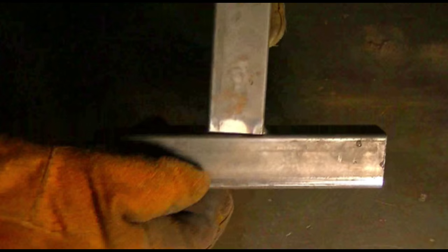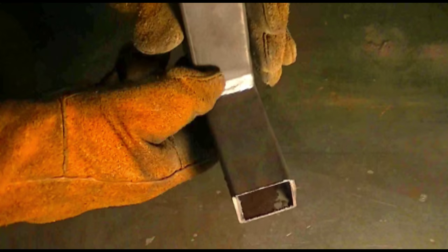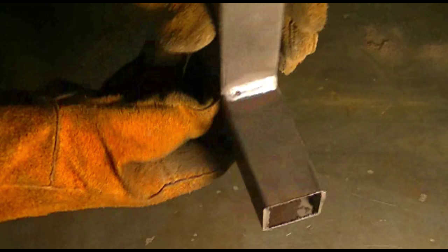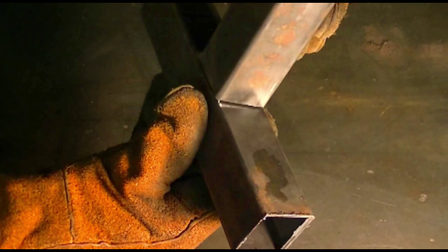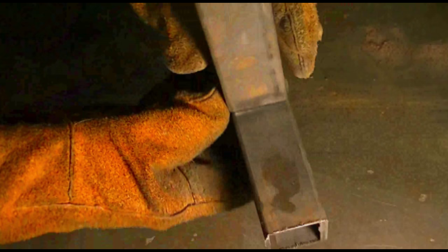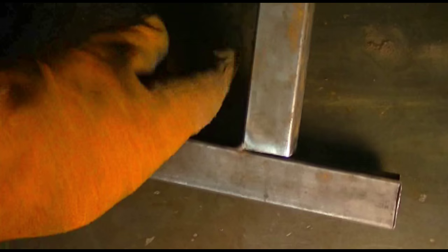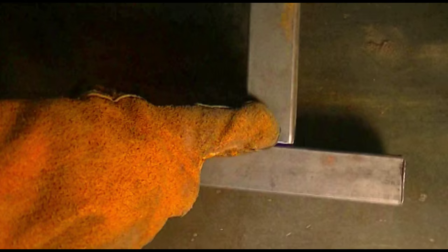Alright guys, so here's the T joint. I did tack one side and I welded a complete bead on the other. There's the bead. You can see there's a little bit of porosity in it, a little divot from where I really didn't clean the steel all that well. But this is just for a demo. I just ran it over a wire wheel real quick. But I don't know how well you can see this, but this joint actually opened up a little bit. And if you flip it over to this side, there's a pretty decent gap there. And that was flush when I started welding. But this is why you want to tack down all four corners of something like a T joint before you weld. So as I'm welding on this side, the heat is pulling the metal this way. And that's why that gap opened up. That's exactly what I said was going to happen.